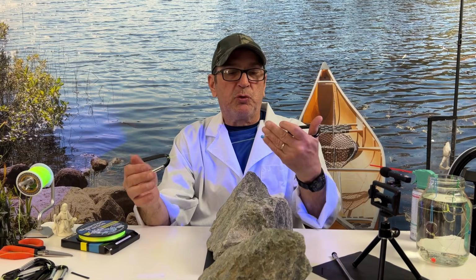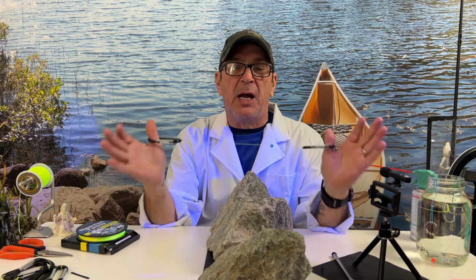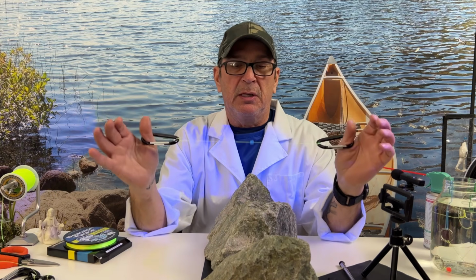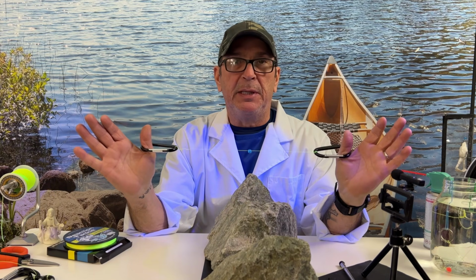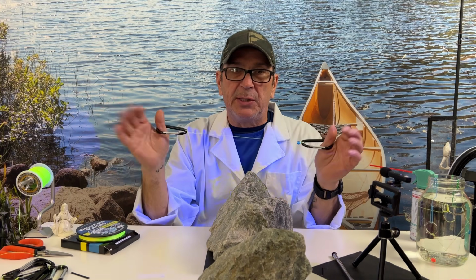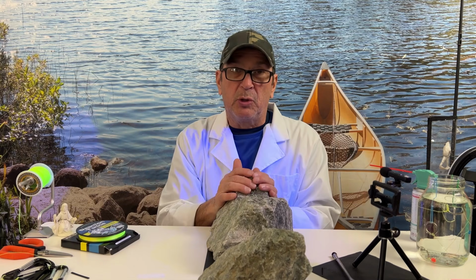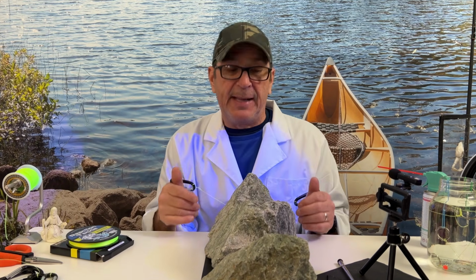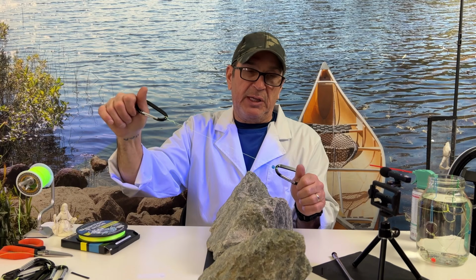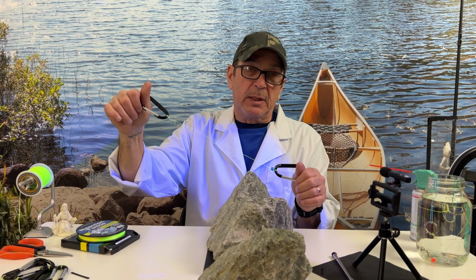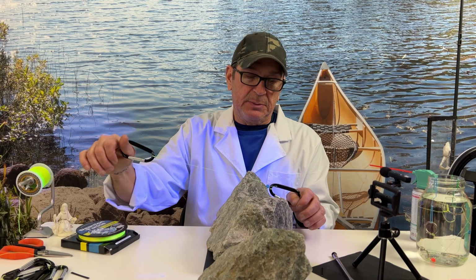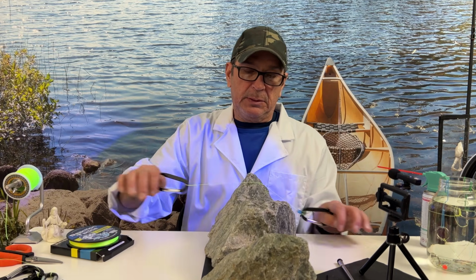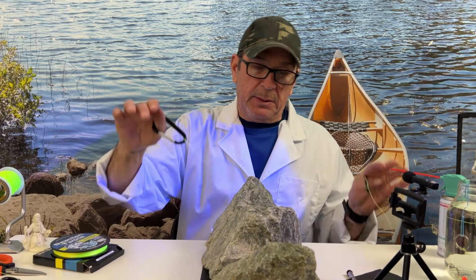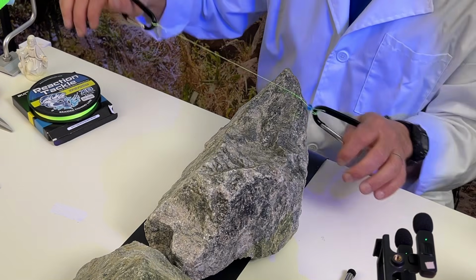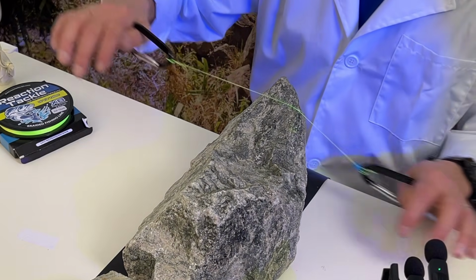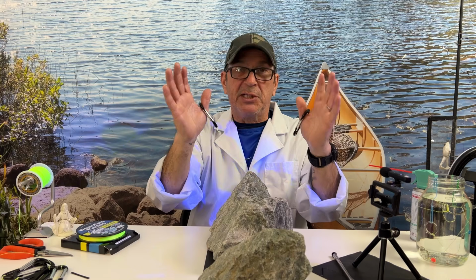Here we go with test 3 of the dry braided fishing line abrasion test, represented by the blue fishing line. Down and up is 1 cycle. If I see 3 cycles on this very sharp structure, I'm very happy. Okay, here we go with test 3 of the dry braided fishing line abrasion resistant test. 1, 2, 3. 3 cycles, that's pretty good.